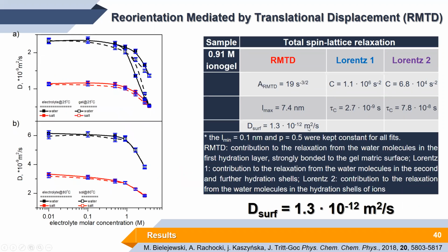And if we now go back to the pulsed field gradient diffusion experiment and look for the diffusion coefficient of either the solvent molecules or the ions, the cations in this case, in the gel phase, so the dashed lines here, we see that the diffusion coefficient is like 10 to minus 9 square meters per second. So field cycling shows us that in the case of our ionogels, the diffusion at the surface of the gel matrix is also much slower than in the case of the bulk solvents.